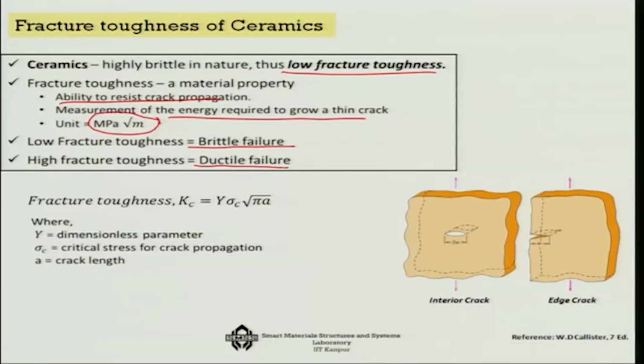Fracture toughness is defined in terms of the product of these three, where Y is the dimensionless parameter, sigma c is the critical stress that is needed for crack propagation, and a is the crack length. So, there can be various types of cracks like interior cracks, as you can see here, or edge cracks. Also, there are various ways in which we can apply the stress, and depending on that the failure occurs; I will talk about it at a later stage.